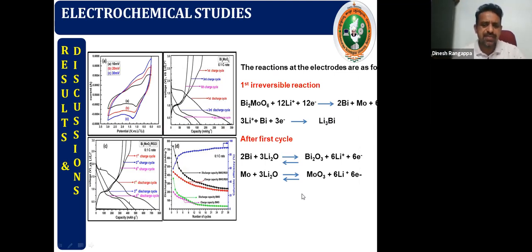So this shows electrochemical studies for the bismuth molybdate and graphene hybrid structure. So we could get very good capacity, about 750 milliampere per gram in the first cycle at 0.1C rate, and finally it stabilized at 400 to 500 milliampere per gram capacity. So the first cycle was irreversible, but after the first cycle we could get a reversible reaction of lithium bismuth molybdate.